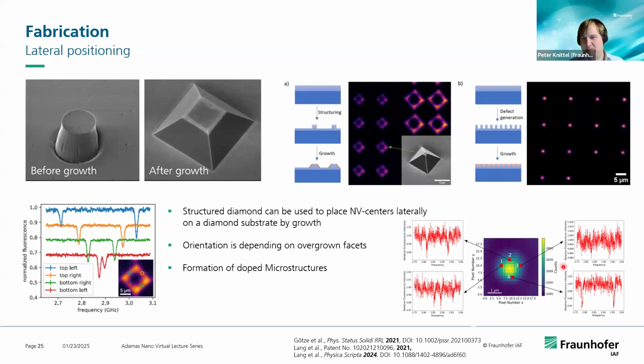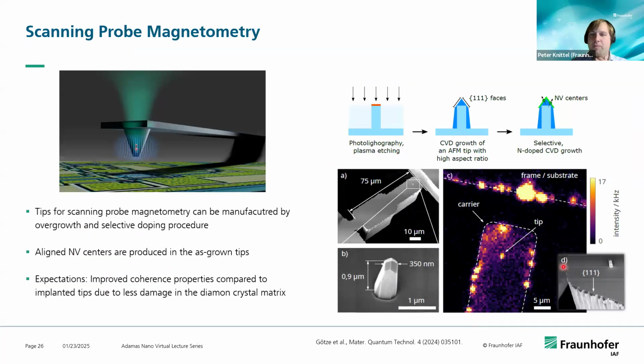Why do you want to place these? For people that are maybe not familiar with these techniques that use the ultimate resolution you can achieve, there is one possibility in scanning probe microscopy applications. You're basically building a scanning probe that contains a single NV center, and you scan this over your surface. With this single NV center, in principle, you could achieve atomic resolution, having an atomic defect, but as you're a bit far away from the surface, you will lose a bit of resolution. But it was demonstrated that few nanometer resolutions are achievable.